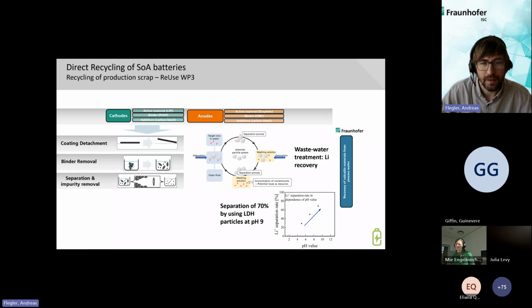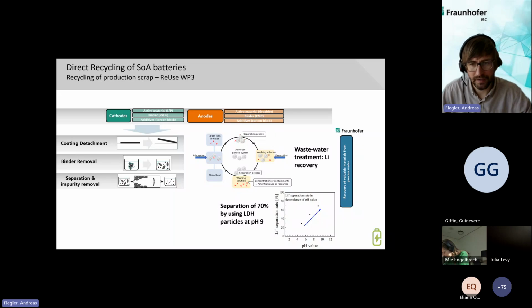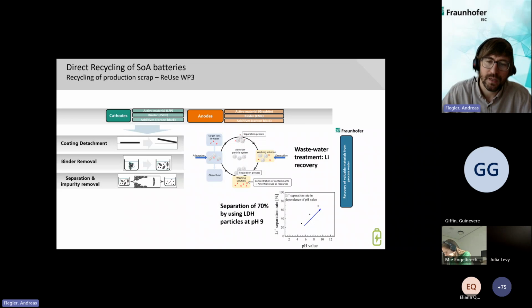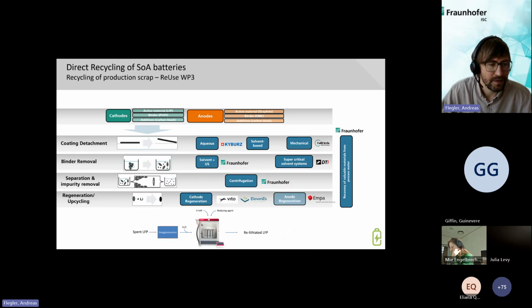process water, and the adsorber particles absorb the lithium ions, and we can separate them by magnetic separation because they are magnetic particles. Then we have a washing solution and desorb these particles, and then we can use them again in a cycle. We see there is a strong dependency on the pH value. You see in this measurement that we can separate more than 70% of the lithium at a pH value of 9. And the last part is the regeneration process.